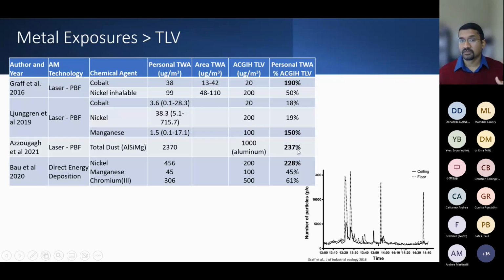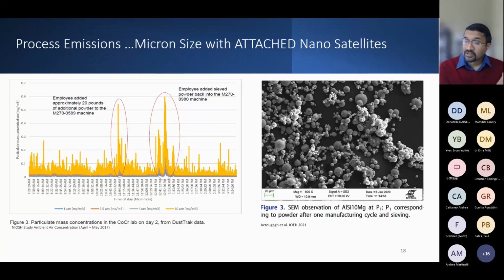But this was key when you think about the weight of evidence, and the literature talks to exceedances from an exposure perspective. We talked about sizes. Raw material inputs are 15 to 45 microns on the smaller size and can go up to hundreds of microns to enable the technology and for the part to be formed.